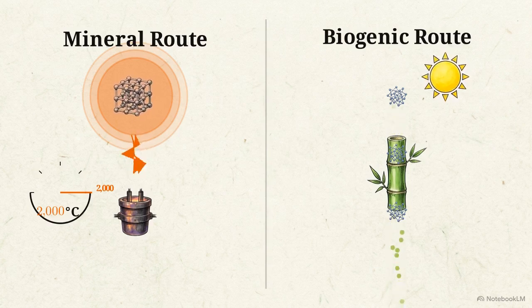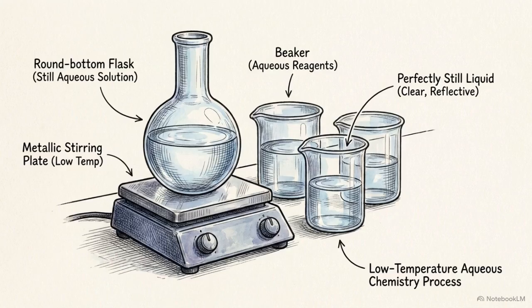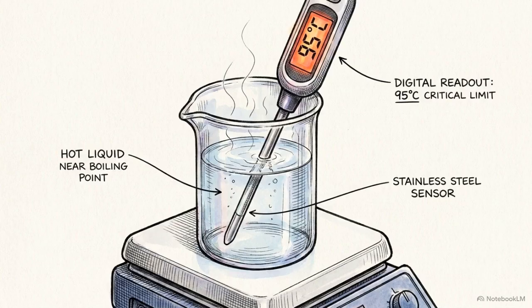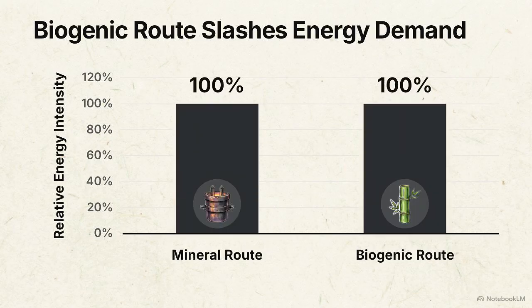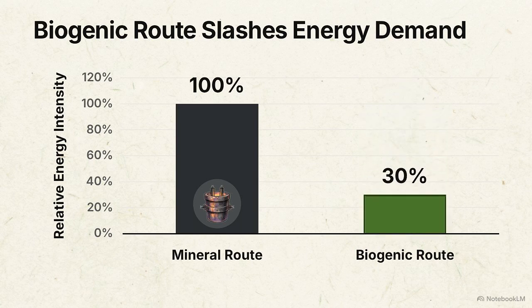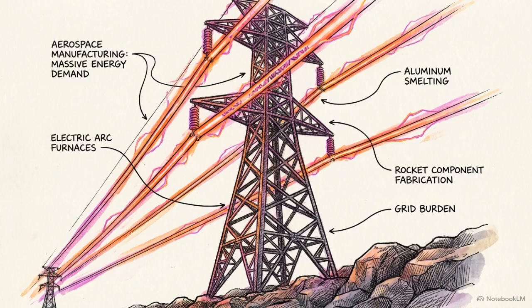Because the plant delivers the silica pre-amorphized, refining it for aerospace use requires low-temperature aqueous chemistry, staying completely below the boiling point of water. Eliminating the furnace stage drops the total thermal energy demand by an estimated 60 to 80% compared to the mineral baseline. Shifting the raw material from mined quartz to bamboo moves the massive energy burden of aerospace manufacturing off the local power grid and directly onto passive photosynthesis.